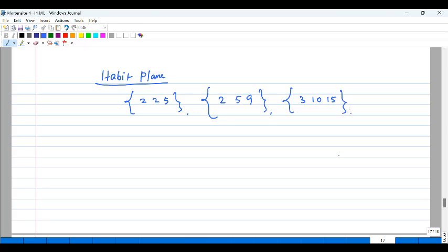So these do not look like the familiar planes that we generally talk about, like the 111 plane, 110 planes, and so on, right? The indices kind of look peculiar. In fact, these are irrational. These are approximated to integers, but actually these are irrational numbers. So this is another question that we have to ask and answer as to why the habit plane indices are like that, why they are irrational.